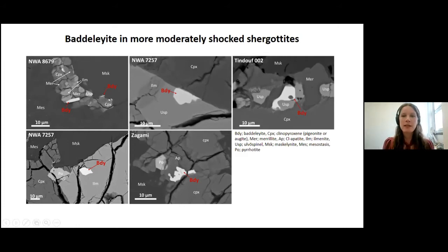So what we did is we took these grains and we did EBSD on the grains that were big enough to potentially go on and date. And I'm going to, in the next few slides, characterize these into 4 distinct microstructural groupings on the basis of their EBSD microstructures. I just wanted to note now, there's a caveat that these are a continuum of microstructures, so these groupings shouldn't be considered absolute. And we actually see very widespread microstructural variability, and sometimes within an individual baddeleyite too.